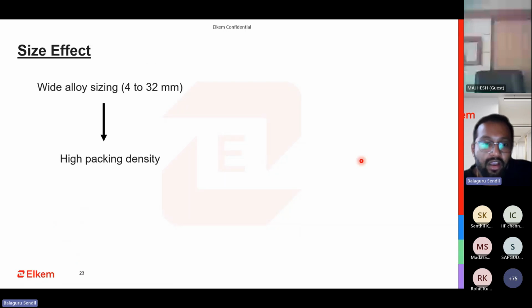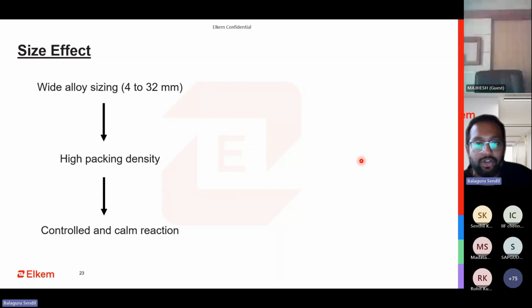As we were discussing the size effect, if you have a wider size alloy, let us say 4 to 32 mm, the packing density is much better. What do you mean by packing density? I'll show you a picture. What happens is that you have a controlled and calm reaction. You have a step-by-step reaction. You have fusion reaction. You don't have the lumps simply floating up.